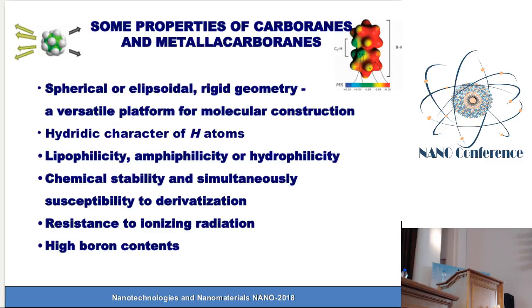The spherical or ellipsoidal rigid geometry provides a platform for molecular construction in three dimensions. The hydrogen atoms connected with borons are hydridic, which means that they have a partial negative charge. They can be lipophilic, amphiphilic, or hydrophilic, depending upon the type of the boron cluster and the substituents attached to the boron cluster scaffold. They are chemically stable, but simultaneously susceptible to derivatization.